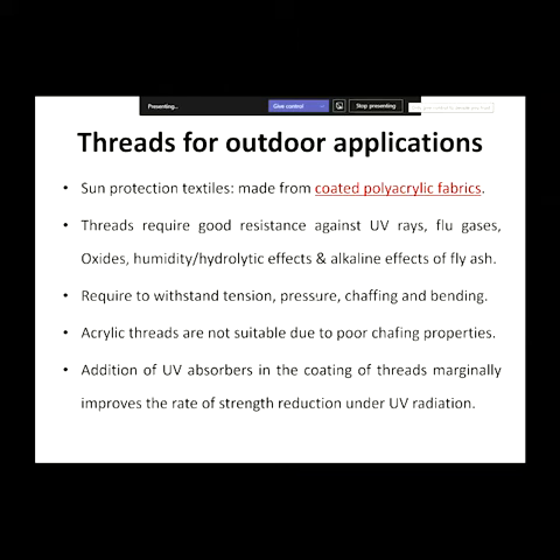So initially, all these sun protection textiles were made from coated polyacrylic fabrics. In the coating, they may use some chemicals which have good resistance against the UV rays. And the main problem with the acrylic thread is they are not good against chafing. Chafing is basically related to abrasion. So these outdoor fabrics have to withstand a lot of tension, compression, pressure, chafing, abrasion, and bending. So they have to withstand these forces or stresses. Unfortunately, acrylic threads are not good in terms of chafing properties. They are very poor. So anyway, for improving the UV absorbing strength, they always add some coating, which is called UV absorbers.